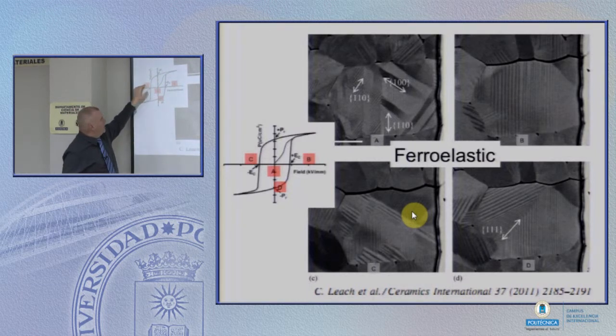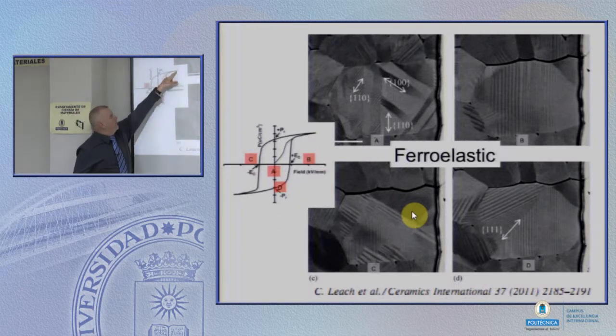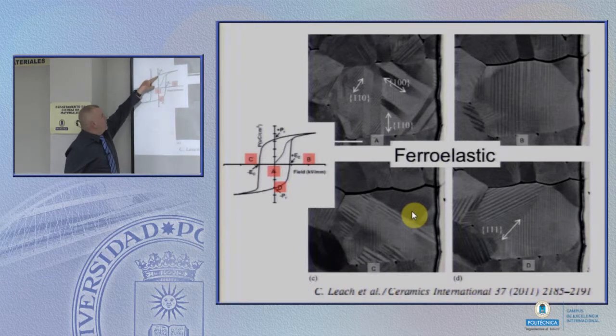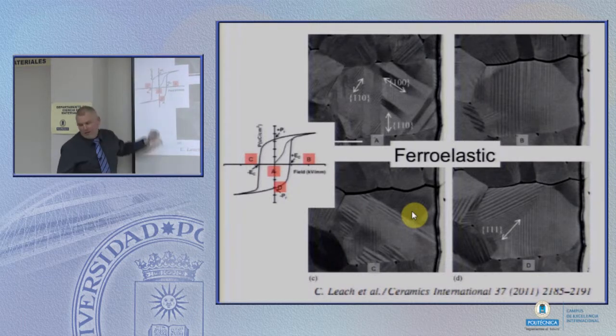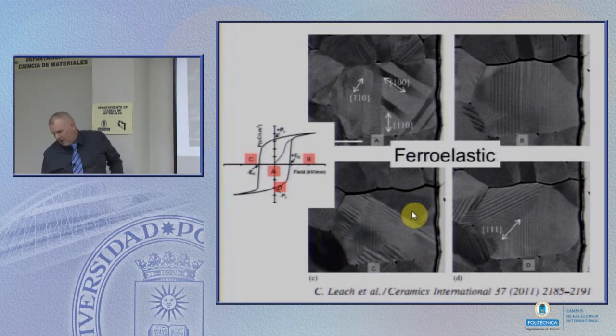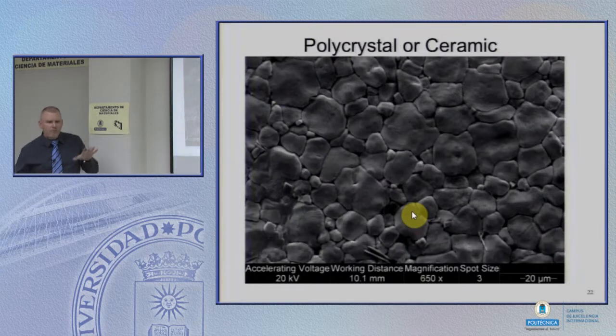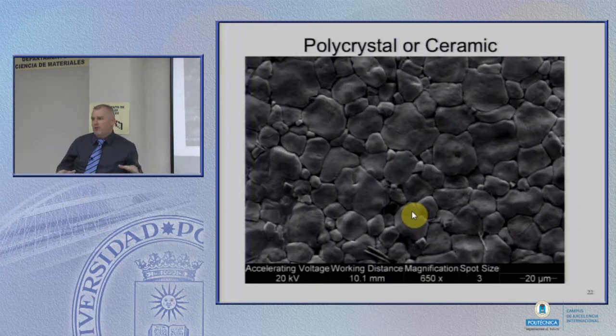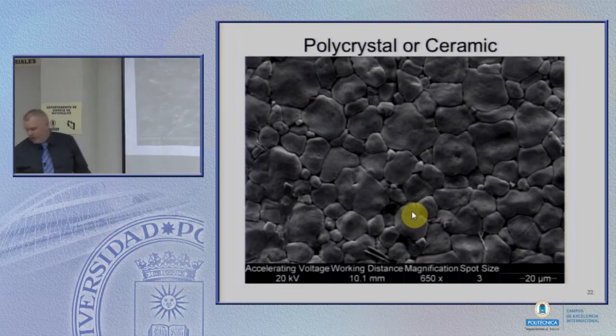Once we apply a field, this is the field axis, the polarization axis. Once we apply a field and then remove the field, we end up with some remnant polarization, some leftover polarization. So thereafter, you can never get back to the center. You end up with a part, one that's here or one that's here. Most of the materials that I work on are polycrystalline or ceramic. So the examples I'm going to show are not thin film materials or single crystal materials. They're polycrystalline or ceramic materials.